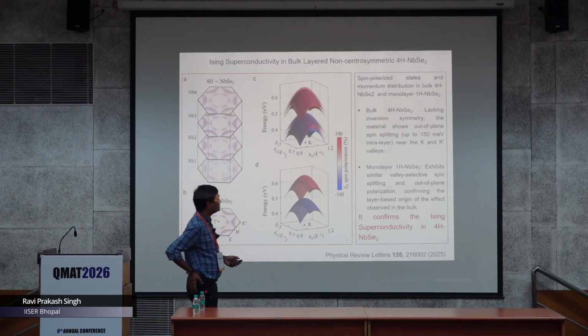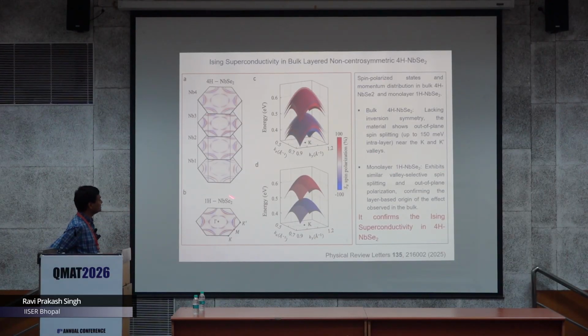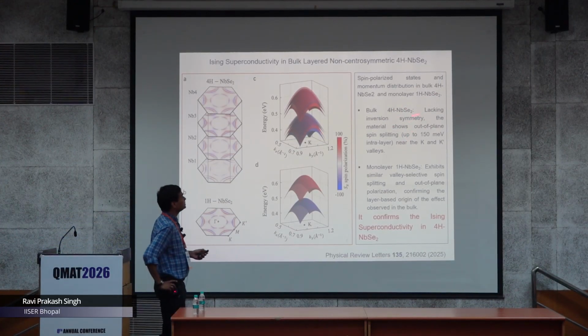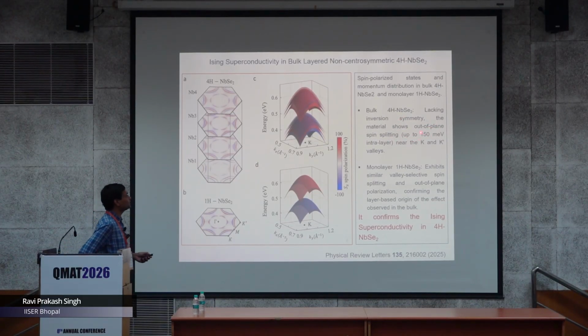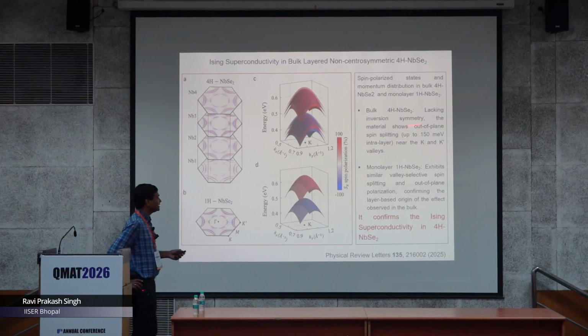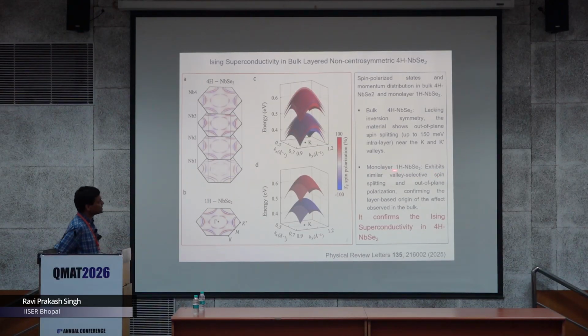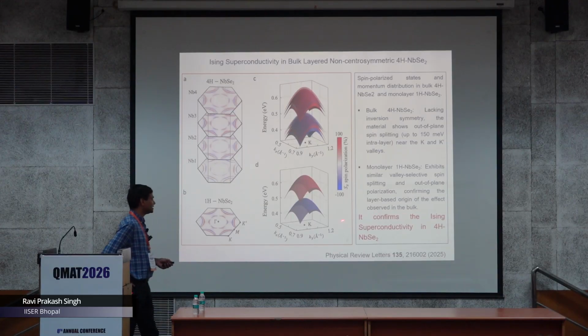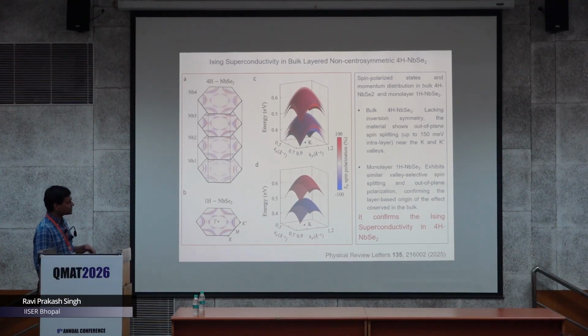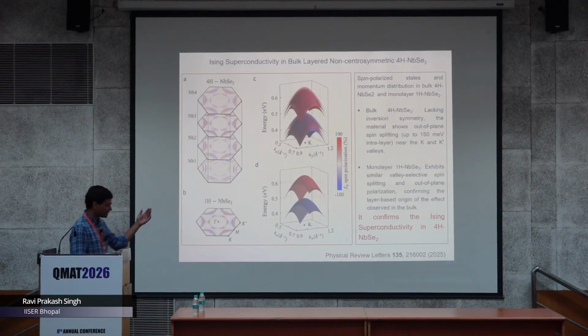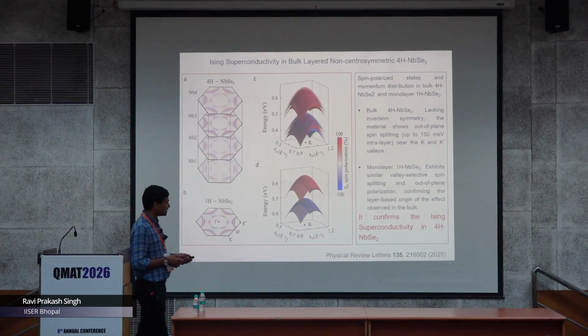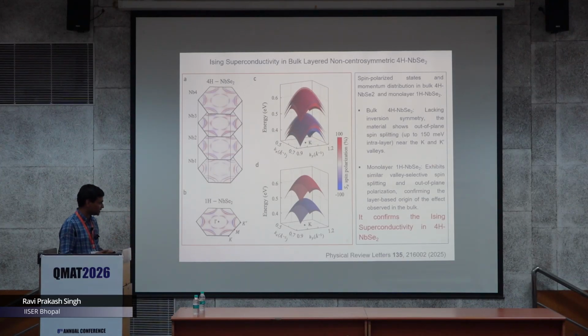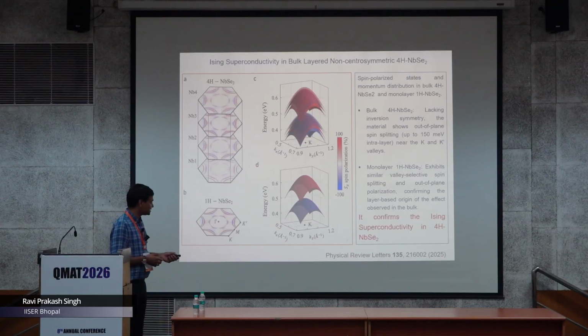And to confirm that, we did DFT, and we found that this 4H NbSe2 material shows out of plane splitting up to 150 millielectron volt, intralayer, near the K and K' valley points, and it is similar to what is present in 1H NbSe2. It confirms that bulk 4H NbSe2 is an Ising superconductor. And we are still working on the superconducting ground state, so it is showing a lot of other interesting properties. We are getting the signature of some triplet also, but I will not discuss that result here.